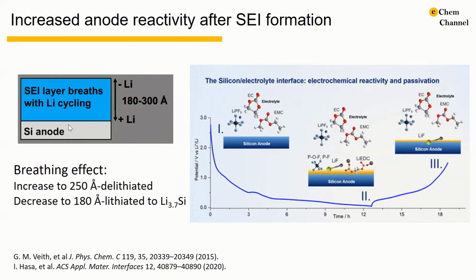In comparison, for silicon-containing electrode, a so-called breathing behavior of the SEI layer has been observed. For example, this work uses neutron reflectometry to determine the thickness and the chemistry of the SEI layer grown on a silicon anode as a function of state of charge and during cycling. The SEI layer contains more lithium fluoride-like components with increasing lithiation and more organic components with delithiation. More importantly, the SEI layer thickness appears to increase to about 250 angstrom as the electrode becomes less lithiated, and the thickness decreases to 180 angstrom with increasing lithium content to Li3.7Si.